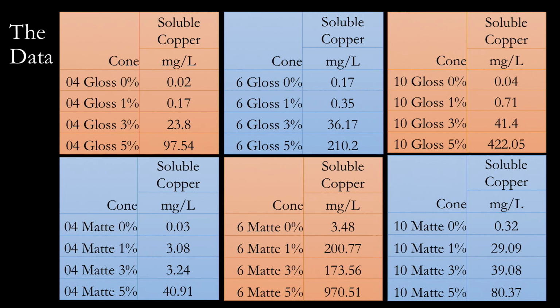So, the data. As you can see, each cell contains a sample set. Our cone 04 gloss, our cone 04 matte, our cone 6 gloss, our cone 6 matte, etc., etc. A couple of trends occur here. Going from 0% to 5% on almost all the samples, the amounts began to increase. The more copper there was, the more material began to leach out into the solution.